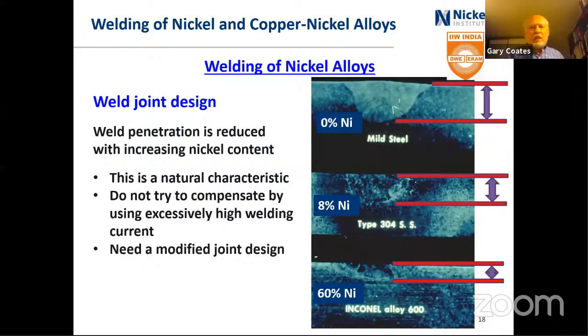When it comes to weld joint design, we understand that the higher the nickel content, the less weld penetration you are going to get. That's a natural characteristic of the material. I'm showing a mild steel here, and then 304, run at the same current amperage, and you get less depth of penetration there. And then an Inconel 600, which has 60% nickel, has even lower penetration.